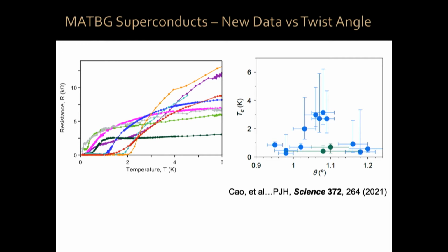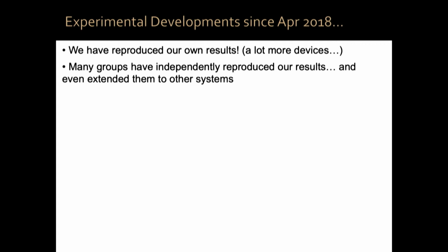We're starting to map the critical temperature at optimal doping of these superconductors as a function of the twist angle. It's a new knob, a new control parameter in physics, which didn't exist before, okay? And as you can see, there is a dome, which roughly goes from 1.2 to 1, maybe 0.95 degrees, something like that. Yeah? Now, even better than reproducing yourself is when others independently reproduce your work. Only then does it become real science, okay?